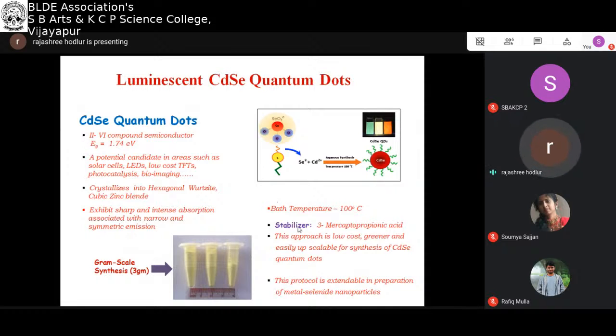And the main advantage is that it was synthesized under ambient conditions, close to the boiling point of water, and we made use of organic molecules like 3-mercaptopropionic acid for controlling the size and shape of the particles. So this aqueous colloidal approach is low cost, greener, and easily upscalable for synthesizing cadmium selenide quantum dots. And it can be extended for other metal selenide nanoparticles as well.